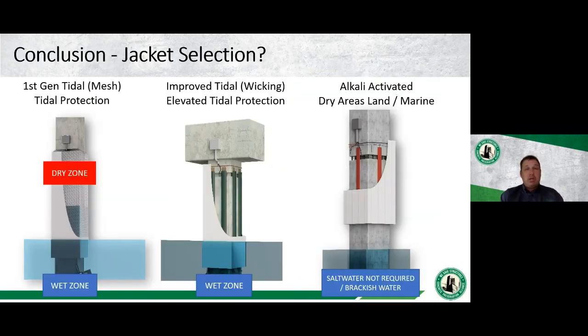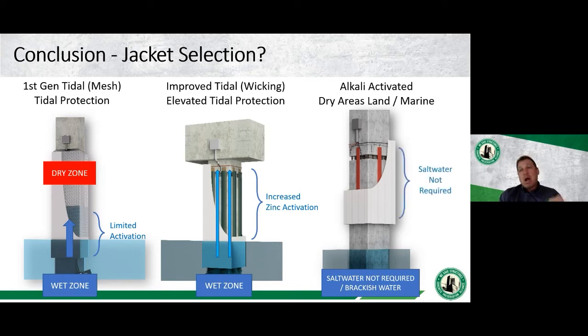So this brings me to the conclusion or the last couple of slides. Basically we started off with the first generation expanded zinc mesh. It worked well in that tidal zone. Then we developed and moved into a wicking technology or the Tidal Plus. With that, we're able to extend that activation or galvanic current protection up to much higher elevations on the pile. And for the areas where we don't have any salt water, or we have a brackish water environment that we cannot rely on the salt water, then we have that high alkaline mortar, where the strip anodes are cast in. And then we have that alkaline activated system as well.